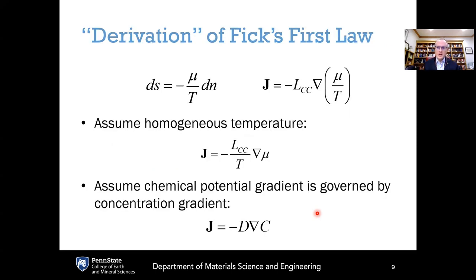So the first thing that I want to do in chapter 3 is to show you how to go from Onsager's formulation of irreversible thermodynamics to derive Fick's first law, which of course was proposed decades beforehand. Now, Fick's first law is governing the flow of matter with respect to a concentration gradient. So the relevant part of our thermodynamic equation for that is how the local entropy, dS, is changing with respect to local changes in concentration of species, dN. And the constant of proportionality between those two from your fundamental equation of thermodynamics is minus the chemical potential of that species divided by the temperature of the system.